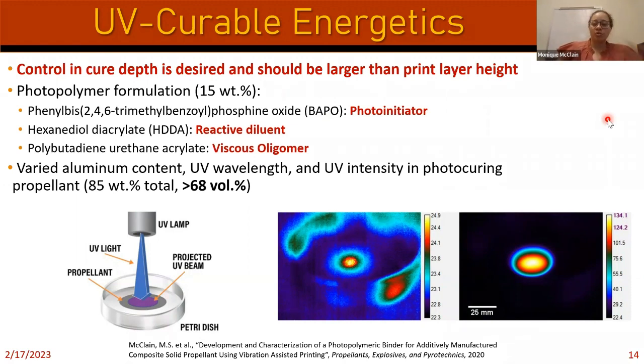In general, when we're talking about our requirements for photopolymers and energetic materials, we need something where we can have a reasonable cure depth. It would not be ideal if the cure depth of your propellant was less than your print layer, because then you would have regions of uncured propellant as you are printing. So it at least needs to hit that.